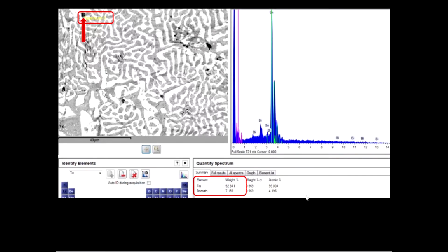If we go down and look at the percent composition, we can see that it's 92.8% tin and about 7.2% bismuth. So it does kind of correlate, right? The higher the peak, the more X-rays were produced, which you get from having more of those particular atoms in that sample. So this is a very tin-rich grain.